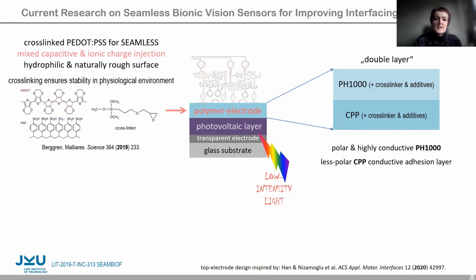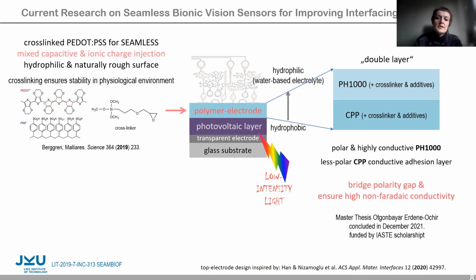It consists of 2 consecutive layers of different PEDOT formulations. The reason for this sequential architecture is the difference in polarity of the organic semiconductor and the aqueous electrolytic environment. The organic semiconductor is hydrophobic, and for good adhesion, the less polar CPP formulation is coated as adhesion layer first. And then the hydrophilic PH1000 formulation can be coated on top.